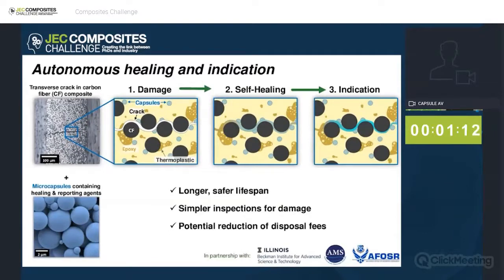To test our material's dual functionality at the micro scale, I make small composite samples about half the size of a matchstick and pull on them under a microscope until they crack, like in my top left image. I then allow them to heal and repeat the same test. To evaluate healing, I can use a computational technique called digital image correlation to track the motion of the carbon fibers and finally calculate the deformations across the entire surface of each of my samples. The second test I conduct is to shine UV light on my cracked samples to confirm that our special dye has activated in the damaged areas. By correlating local fluorescence with local recovery, I'll be able to verify simultaneous self-healing and damage indication.